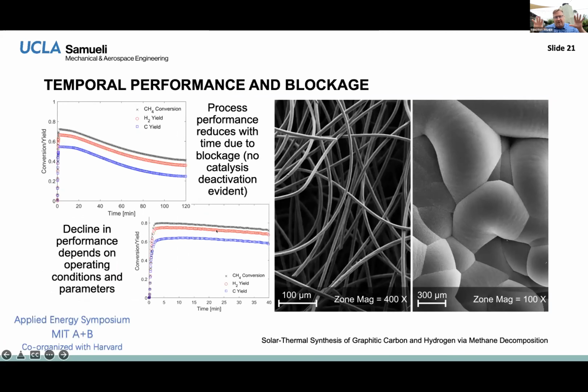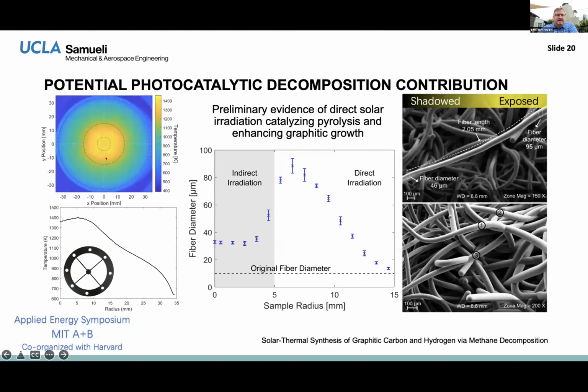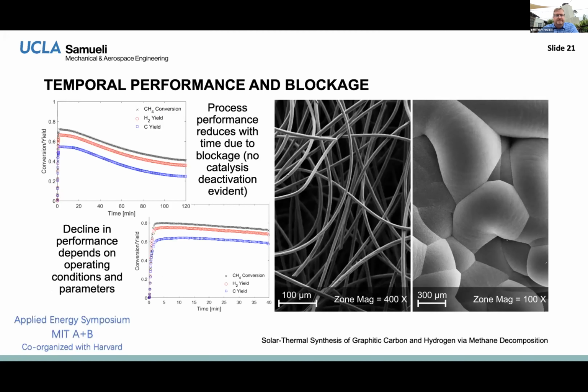So even with all of that bypass, we're getting 70% conversion of the total input, which is surprising to me. In fact, I'm thinking that, I worked in free convection, there may be some density changes that are actually channeling flow toward that middle region, where the temperature is higher. We haven't done a full CFD simulation of it yet, but that's a surprisingly high number. We are, of course, working on making this look like a bullseye, much more uniform in temperature. And then we expect to have hydrogen yields that will probably be in the 90%. Yeah, this is very good.